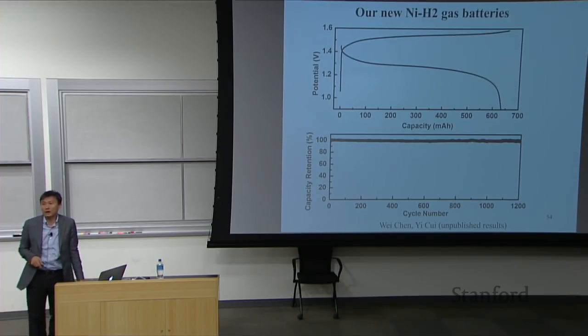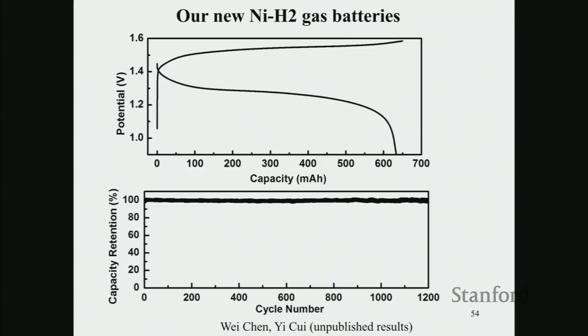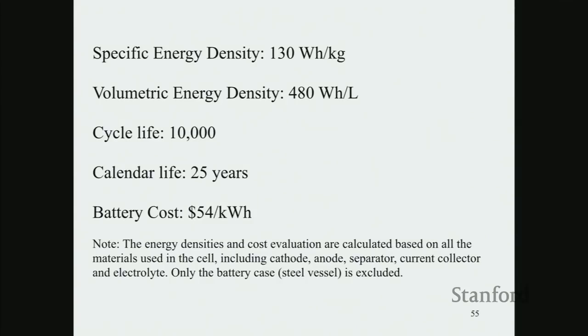These show you more than 1,200 cycles without decay. It's about 1.3 volt aqueous solution battery, very low cost. And these have shown this quite amazing performance. For an aqueous system, this can potentially get up to 130 watt hours per kilogram. And lead acid is only 30-40. The usual redox flow is about 30-40. This you are talking about 3 times higher. And the volumetric is not bad. The key thing is we think the cycle life can go to 10,000 cycles. We have done a limited couple thousand cycles, virtually without decay. And this is extremely important. Calendar life could be 25 years.